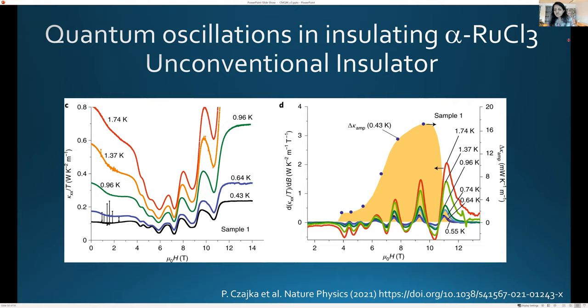I think, though, that one of the challenges would be the field range, right? This is a sort of low field range that these oscillations are reported to be largest in. And as you saw earlier, the oscillations grow with magnetic field. So I expect one of the challenges will be seeing large enough oscillations at these fields, just to explain why technically it would be challenging, but yeah, they haven't been reported yet.